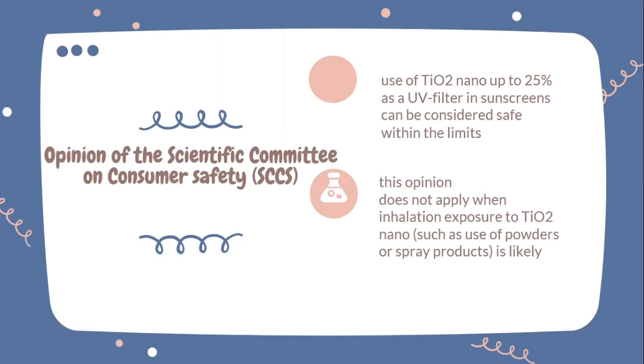So, to add, in the SCCS opinion, the use of pigmentary titanium oxide in a typical hairstyling aerosol spray product is safe up to a maximum concentration of only 1.64% for the general consumer and 1.0% only for hairdressers.